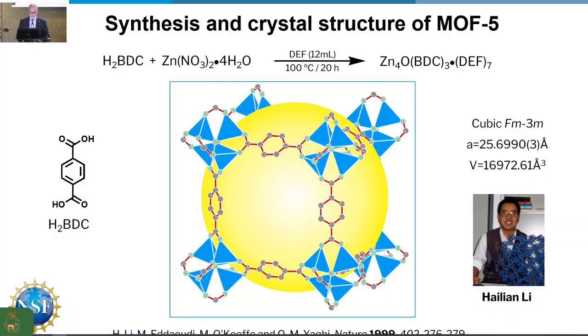Well, we were really now very excited, and in 1999 we reported MOF-5, which turned out to be an archetypical MOF, and we put the yellow ball there to indicate the space within which you could incorporate structures. And the reason these structures are just so touching, I would say, is that they're made from clusters, in this case tetrazinc carboxylate clusters that have been around since Bragg. I mean, Bragg was the first to characterize these using single crystal X-ray diffraction. They were sitting there for almost 100 years before we came along and linked them up to make frameworks.